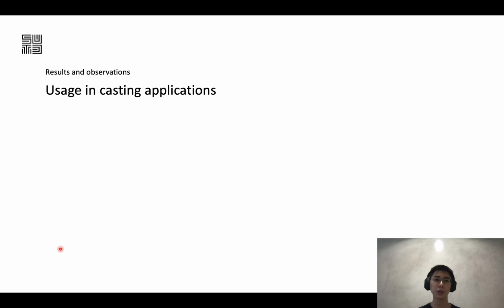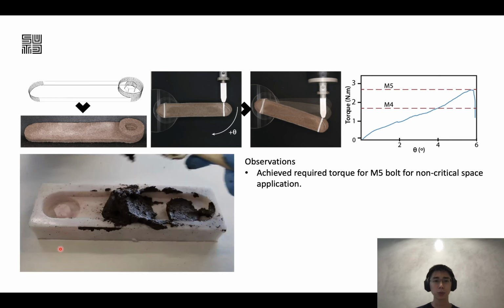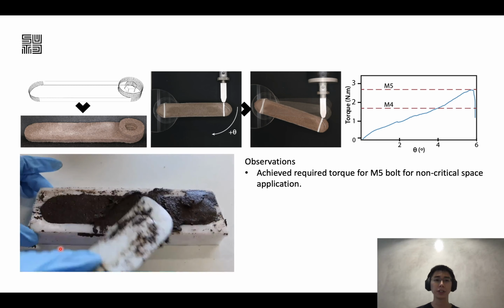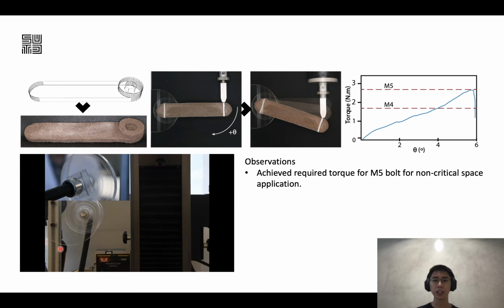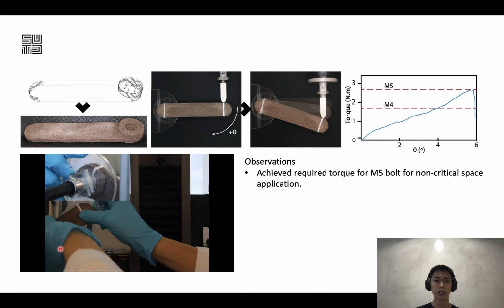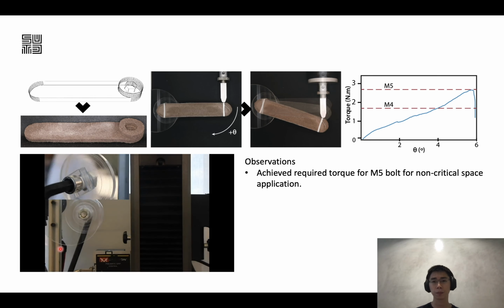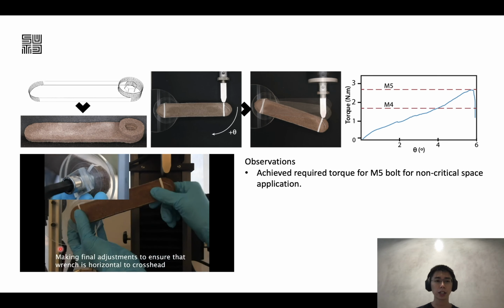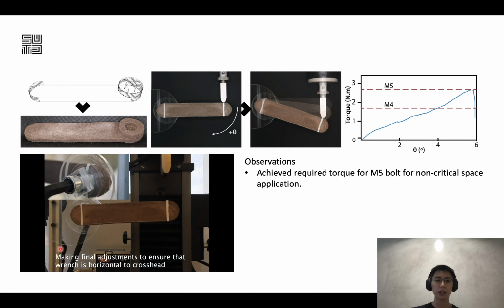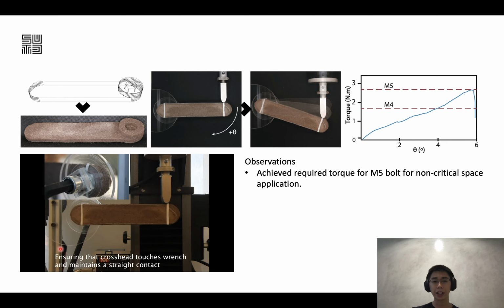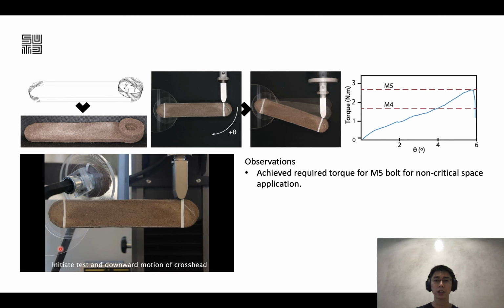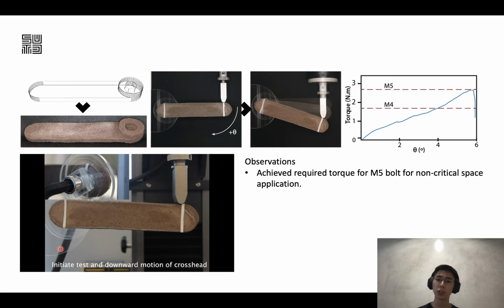Now, let's move on to the application portion. First, in casting. So we try to cast a functional object, which in this case is a wrench, and we try to subject it to a downward force using a universal testing machine. And what we realize is that as we subject more and more downward force on an already tightened nut, the wrench actually fails at about the top above 2.75 Newton meters.